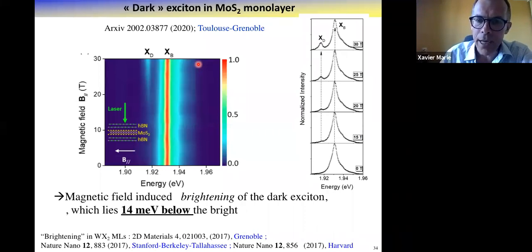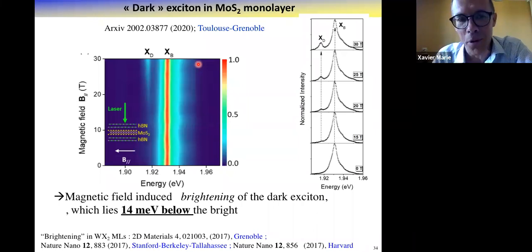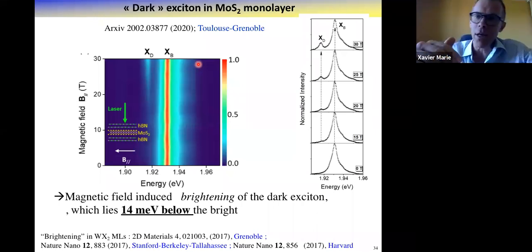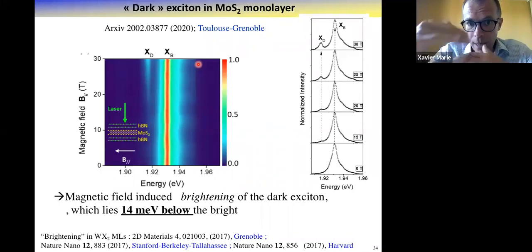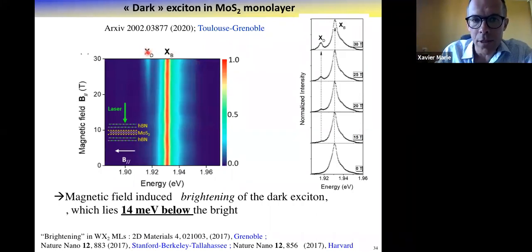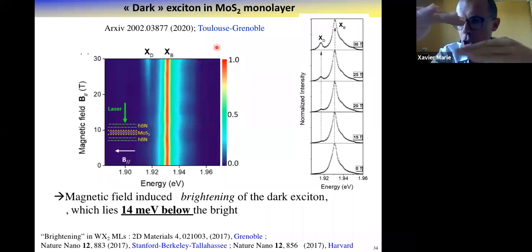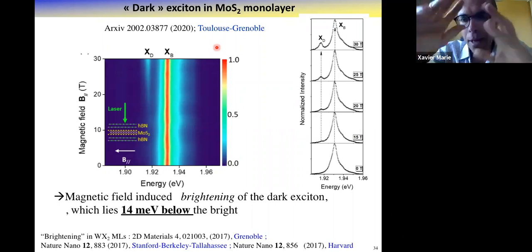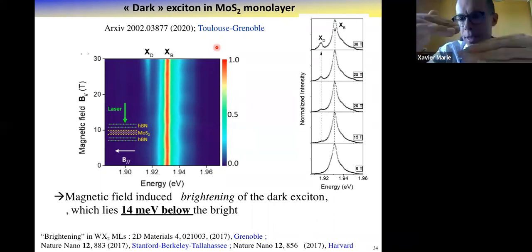When you look at the calculations, you have at least 50% of the calculations which say it's below, 50% of the calculations which say it's above. The problem is not so easy because when you consider what are the key ingredients which govern the energy difference between the bright exciton and the dark one, you have the spin orbit splitting in the conduction band in the single particle picture. Most of the calculations, and now my vision is here, give something of the order of 3 or 4 millielectron volts. So basically, the two conduction states are almost degenerate. But this is not the end of the story.